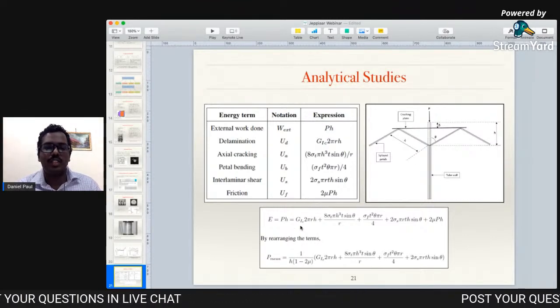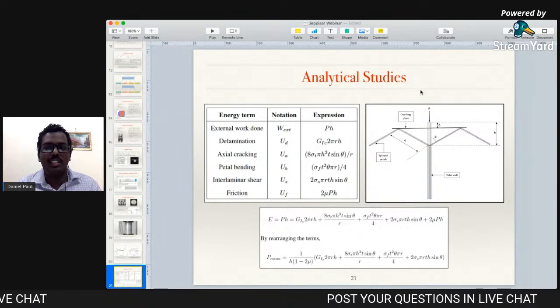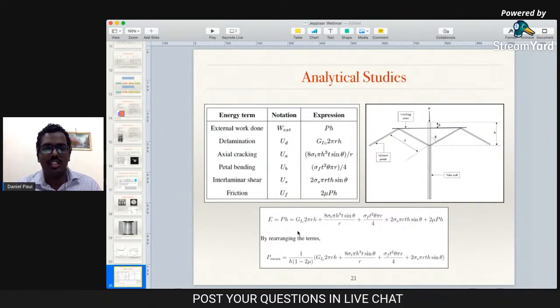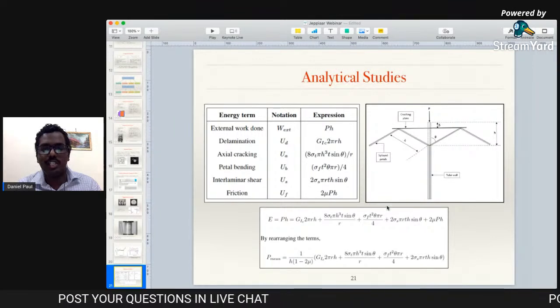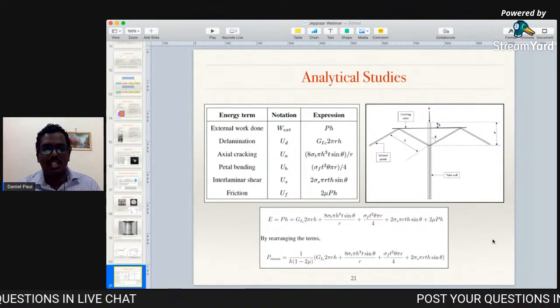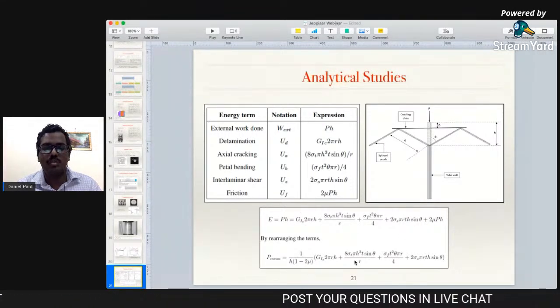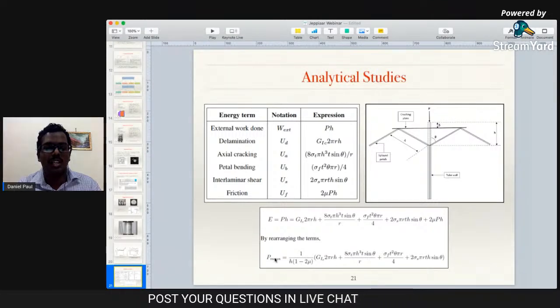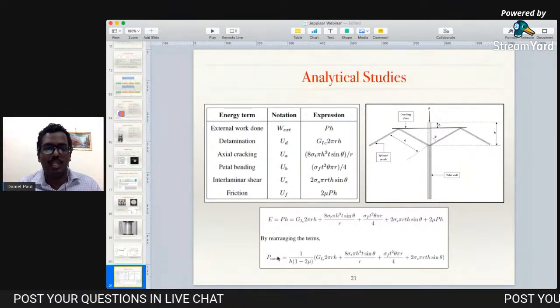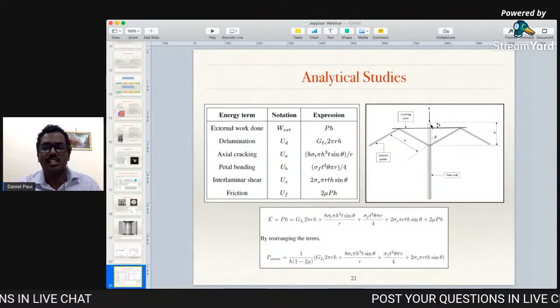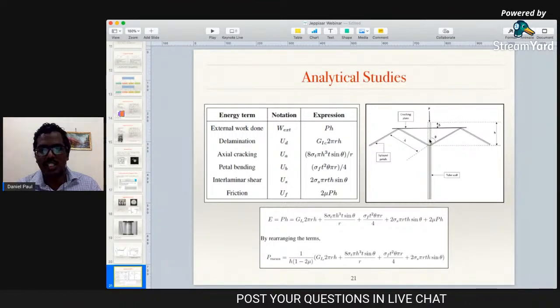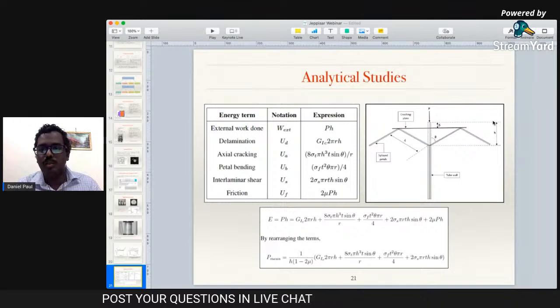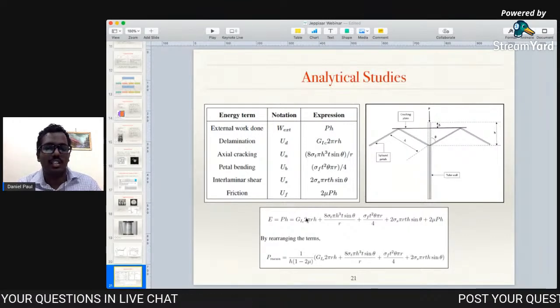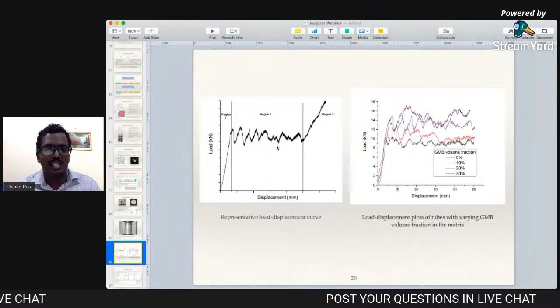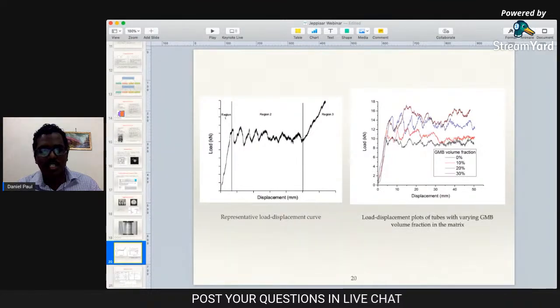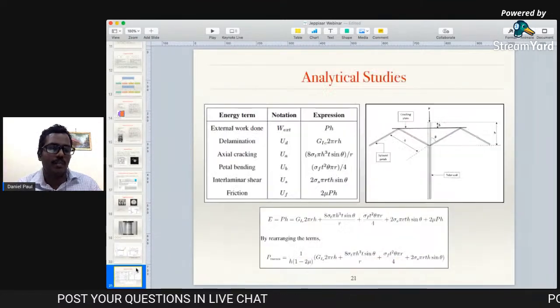So what we can do is equate the input energy, that is the external work done, with the sum of all these energy absorption terms, and then by rearranging these terms in a proper way and simplifying the equation, we can find the mean load which the structure experiences during one particular crush cycle. This is the same as the mean crush load in this plateau region.